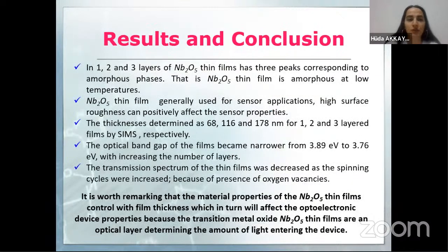Result and conclusion. The 1, 2, and 3 layers of niobium pentoxide thin films show an amorphous structure in X-ray diffraction, and niobium pentoxide thin films are generally used for sensor applications. High surface roughness can positively affect the sensor properties. Then the thickness is determined as 68, 116 and 178 nanometers for 1, 2, and 3 layered films by SIMS, respectively. Then the optical band gap of the films became narrower from 3.89 electron volt to 3.76 electron volt as the number of layers increases.